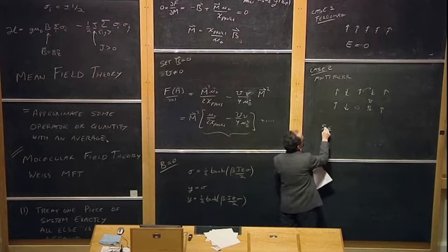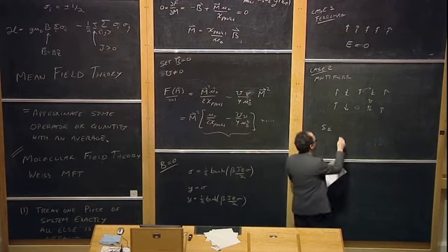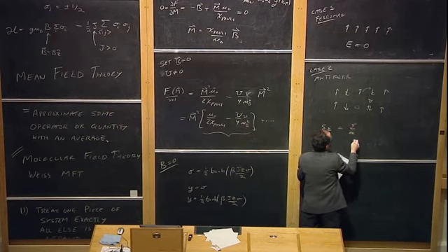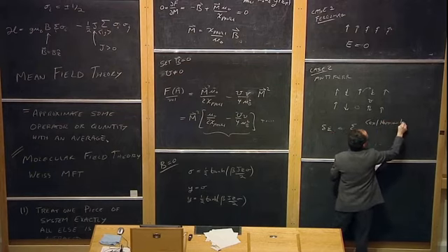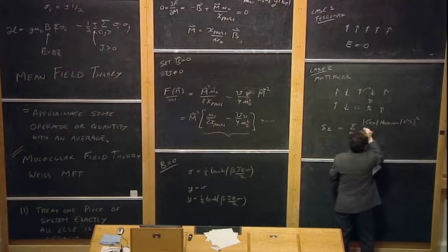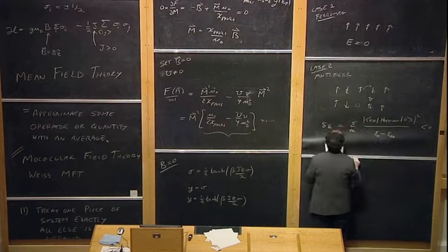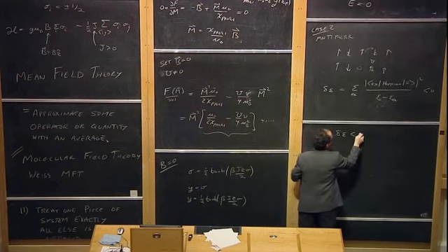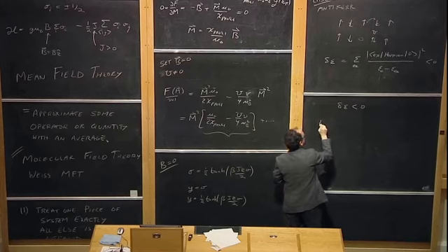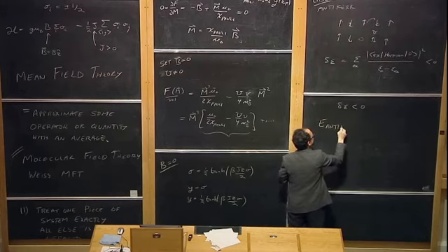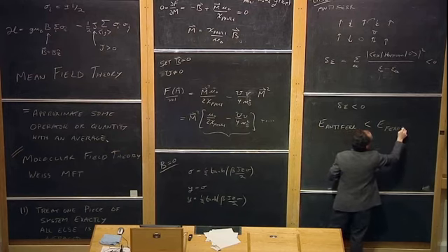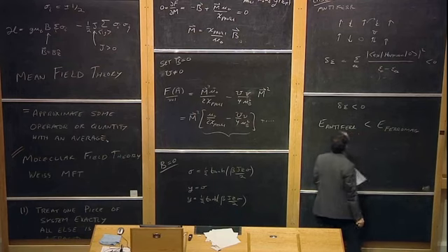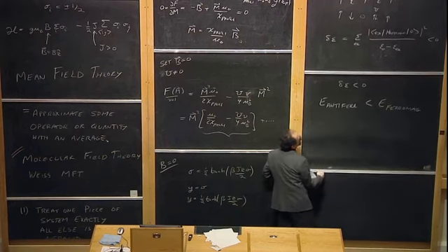And so in second-order perturbation theory, due to this sort of hopping process, you get a shift in the energy, which is the sum over all possible excitations of the excitation, hopping Hamiltonian, ground state, squared, over energy 0 minus energy of the excited state, and this is less than 0. So in fact, the change in energy is less than 0. So the energy of an antiferromagnet is less than the energy of a ferromagnet when you have 1 electron per site in this Mott insulator limit.